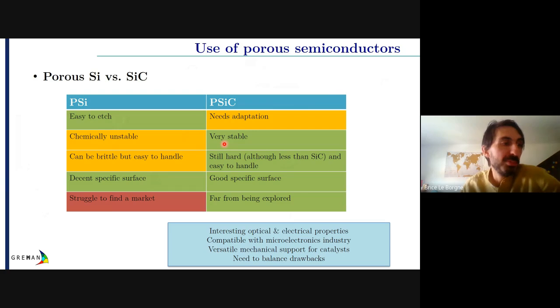So to conclude on the drawbacks and the good points of each of these two materials. So porous silicon is easy to etch. We all do it, almost all of us. Porous silicon carbide is not so easy. It needs adaptation, but when you master the process, it's simple enough. The porous silicon is chemically unstable, so you often need something to stabilize it. So that's what we're going to talk about after. While the porous silicon carbide is very stable, that's really good. Porous silicon can be brittle also. That can be a problem depending on the porosity you need, but it's easy to handle, so that's good.